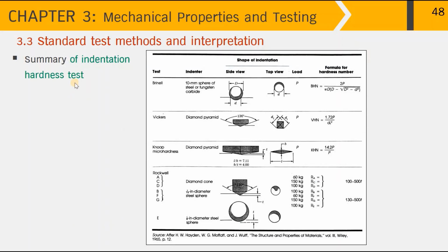And finally, I would like to summarize all the indentation hardness tests over here, ranging from the type of test, the indenters utilized, and what happened when we apply the indenter on the metal surface, and also the top view. When we obtain the load, we can calculate the hardness number according to the formula provided in the column on your right hand side. Firstly, on the Brinell, we use a steel ball diameter of 10 mm, or we can also use a tungsten carbide ball as well. That will produce indentation diameters of small d, as you can see from the top view here. The load measured can be used to obtain the BHN value by putting it into this equation.